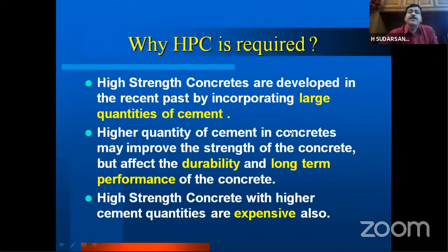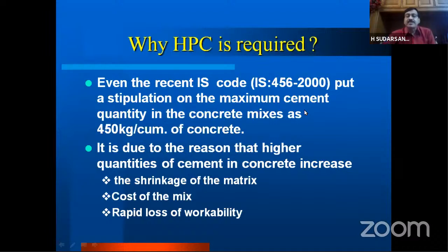So then, why is this high performance concrete required? You heard about high strength concretes which are producing a compressive strength of 50 megapascals or 60 megapascals. The high strength concretes have been developed by incorporating huge quantities of the cement. But actually, if you incorporate more and more quantities of the cement in concrete, it is actually affecting the durability and long-term performance of the concrete. And because we are using more cement quantities, the high-strength concrete is also expensive. Naturally, because cement is expensive, the high-strength concrete is becoming expensive.